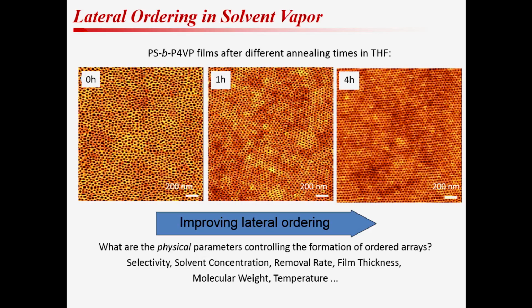and we start to get very high order in the film. It's trivial. Take a film, spin coat it. Spin coating is done every day in industry. Throw it into a solvent vapor. Solvent vapor imparts mobility. Non-favorable interactions between the components wants to reduce the number of defects in the system.